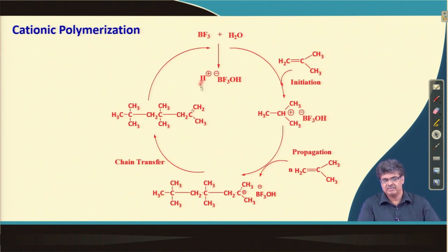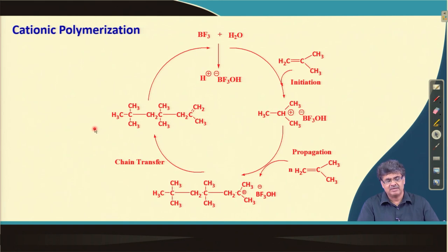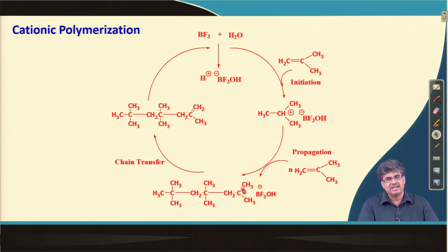In the mechanism of cationic polymerization there is an initiation step followed by a propagation step. Inherently, two propagating cations cannot react with each other and terminate, but chain transfer reactions can occur — chain transfer to monomer, to the counter ion, or to solvent — which can quench the cation and terminate the chain. So the key difference from radical polymerization is that while two radicals can terminate each other, two cations cannot; termination in cationic polymerization happens only through chain transfer reactions.